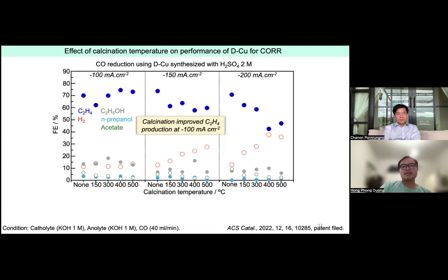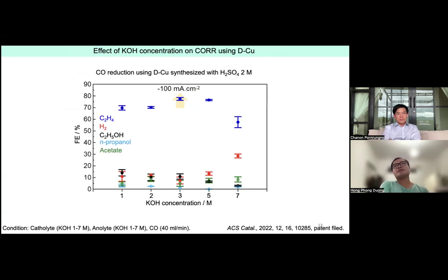Okay, and we also performed the optimization of the electrolyte concentration. I have to mention that the electrolyte concentration is also a very important thing in this field, because several studies show that the concentration of the cations, which can be either potassium or cesium or sodium, can affect significantly the selectivity of the reactions. And we found that from 1 to 7 molar of KOH, the 3 molar was the best one to get the efficiency of 76% for ethylene production in terms of Faradaic efficiency.